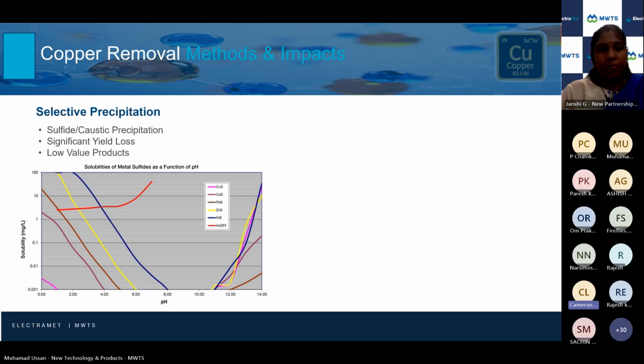Now, when you use sulfide as the chemical, the solubility curves shift. If you look at the bottom left, that little pink line is copper. So you can get copper out very well to very low concentrations, but it has to be very, very acidic. The problem there is sulfide plus acid makes hydrogen sulfide gas, which is very, very toxic. So the safety concerns are not conducive for a lot of facilities. And if you get a little more alkaline, even at pH 2 to 4, you now see all the nickel come off, all the cobalt come off, mainly that blue line. So now you're losing all of your products.